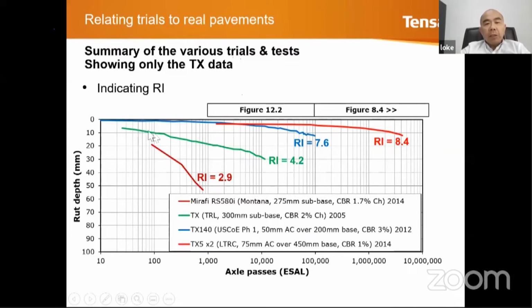So this is the TRRL result, which I've already shown you, up to 10,000 passes. We have about 30 millimeters of settlement or rutting. This is the US Corps of Engineers result, 100,000 passes, whereby you have less than 12 millimeters of rutting. And this is the Louisiana Transportation Research Center's test, which is up to 4 million passes. And again, you have less than 12 millimeters of rutting.